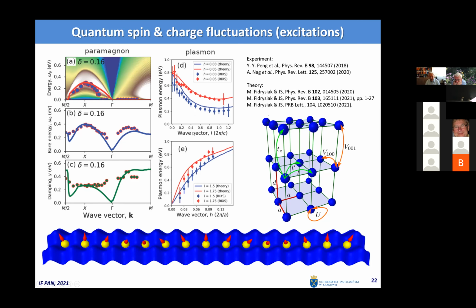And you could say, why paramagnons? You have washed out antiferromagnetism, this anti-parallel orientation of neighboring spins. But look, if you excite a magnon in a magnetic system, what does it mean? Well, it means you reverse one of the spins. So out of a singlet of S equals 0, you create a triplet. So it's a singlet-triplet magnetic transition. That's the creation of a magnon. And at the bottom, you can see as if it was just the spin wave, the precession out of phase. And of course it's damped, which is not explicitly shown, but essentially the thing is the same. And the beautiful thing about it is that you can get those paramagnons, even though the damping is so important.